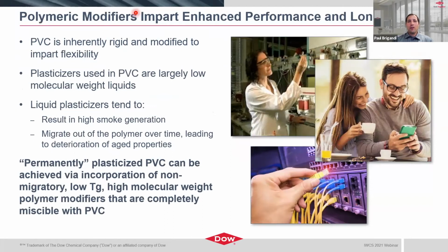So when we look at the polymeric modifiers, we're really looking at them to enhance performance and longevity of the PVC material. PVC in and of itself is inherently rigid, and we typically are going to modify that polymer to impart some flexibility to it. Plasticizers used in PVC are typically low molecular weight liquids, so phthalate-based. And these liquid plasticizers tend to result in higher smoke generation and migration out of the polymer over time, which really leads to deteriorated aged properties.